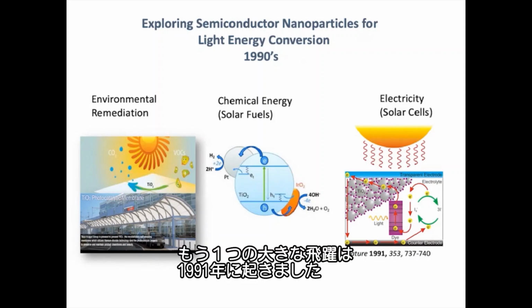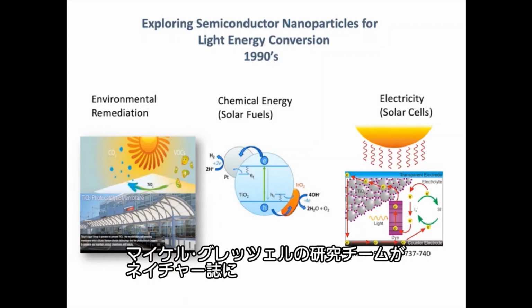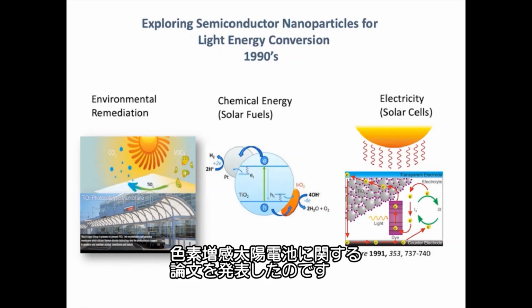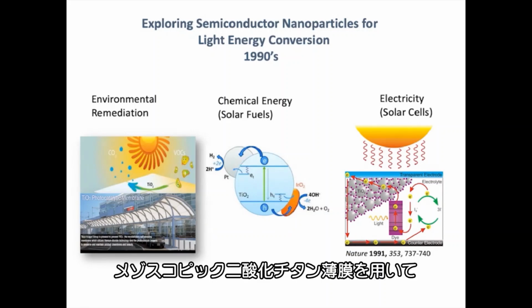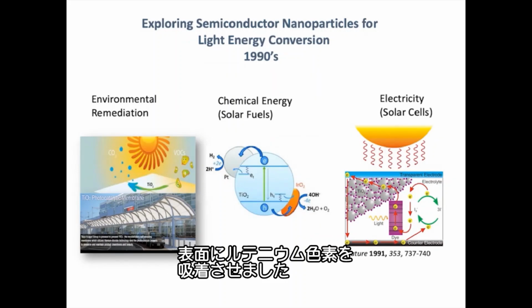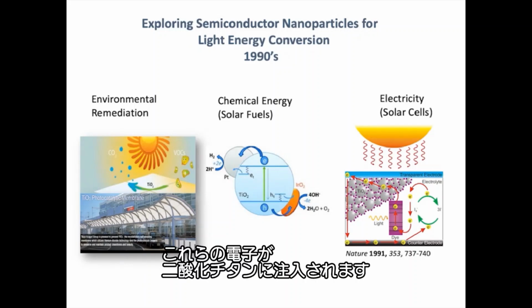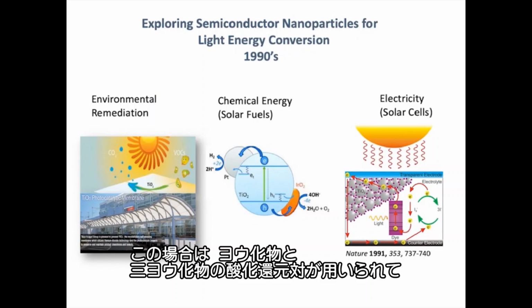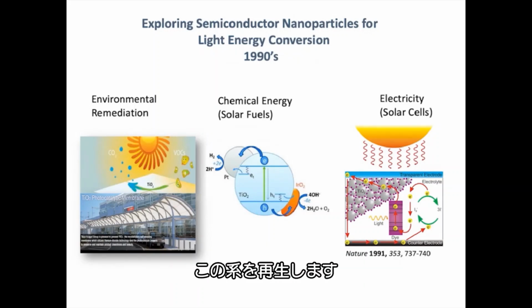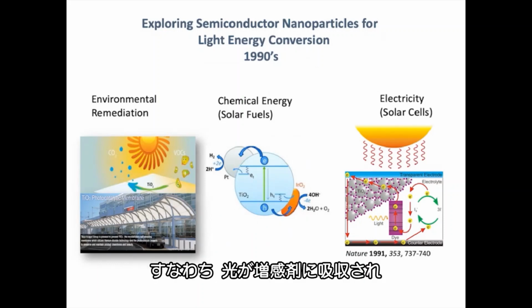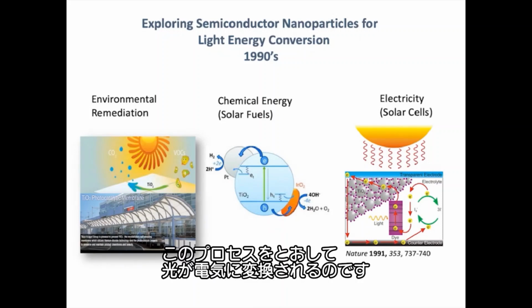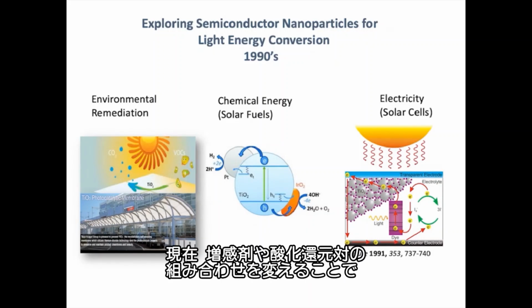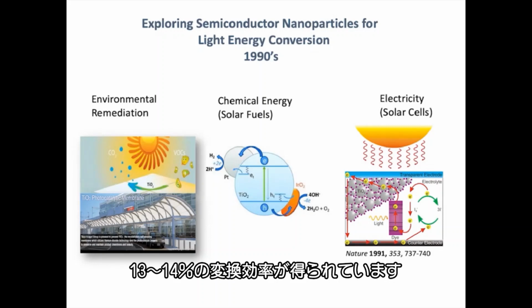Another major breakthrough came in '91 when Michael Gratzel and his co-workers published a paper in Nature on the dye-sensitized solar cell, where they used mesoscopic TiO2 films on which they put a ruthenium tris-bipyridyl dye as a sensitizer. When you excite this dye, you get electron transfer to TiO2, and the redox couple, in this case the iodide/triiodide couple, regenerates the system. So basically the light is absorbed by the sensitizer and converted into electricity through this process. This gained a lot of momentum in the next 20 years or so, and today about 13 to 14% cells have been demonstrated with different sensitizers and different redox couples.